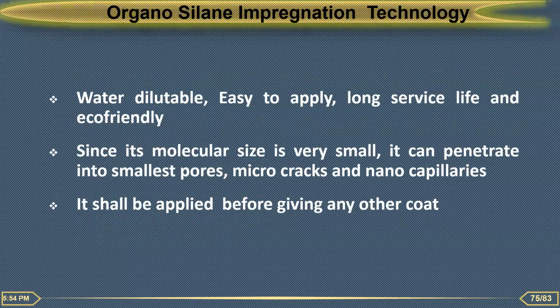Organosilane technology is a very commonly used method. It is water dilutable, easy to apply, and has a long service life. And another advantage is that it is eco-friendly. The molecular size is very small. It can even penetrate the micro cracks and nanocapillaries. The only thing is that it has to be applied fresh on the concrete surface without giving any coat, because once you give the coat, it cannot diffuse into the concrete.